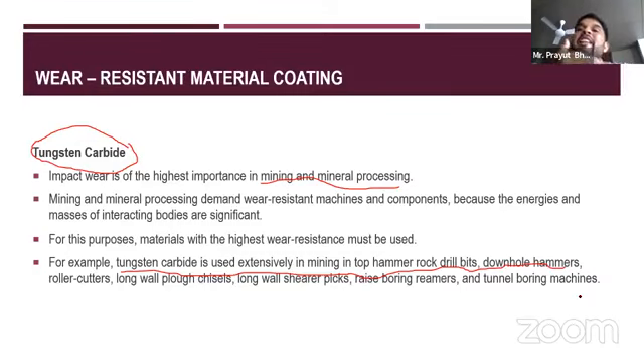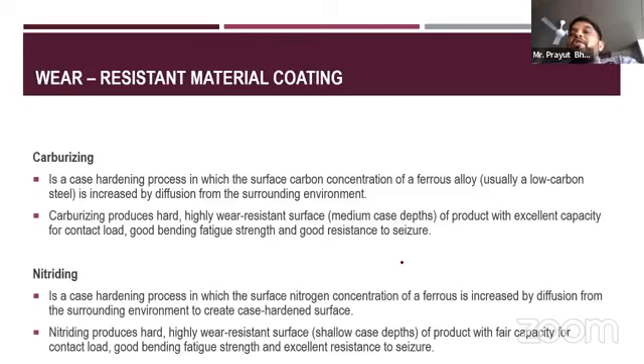So normally if the same blade is used in a raw form, and if you apply the tungsten carbide coating over it, the life of that same component can exceed 5 to 7 times. So that's what this wear resistant material does. It's again a very, very popular coating. It's comparatively low cost; compared to it, silicon carbide is a high cost. Tungsten carbide is a bit higher cost than some, but with the other alloys that we discussed, this is low cost, and the application is also very easy. So it's popularly used.